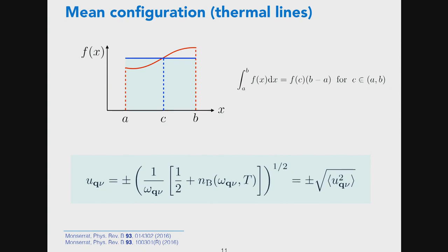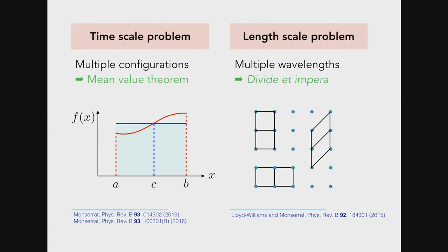We actually now have extensions to this to relax both the harmonic condition on the lattice dynamics and the low order in the electron-phonon interaction. In those cases, we cannot find solutions with a single point, but we can find solutions with very few points, of the order of 10, say. So this is an example of the sort of trick that we use to reduce the computational cost of these calculations. We also very carefully choose which supercells we use in order to capture the relevant vibrations of the lattice, but I won't go into more detail about this.